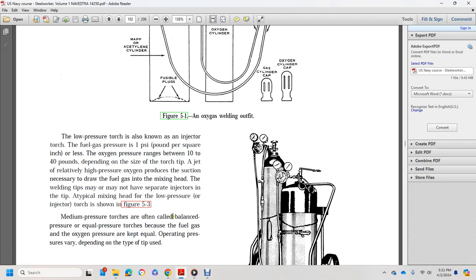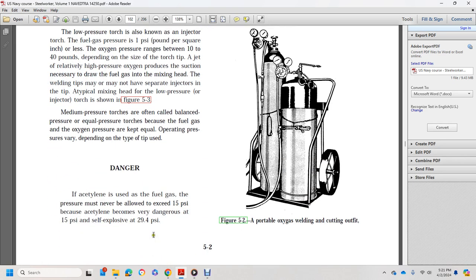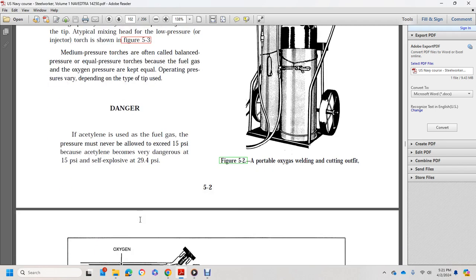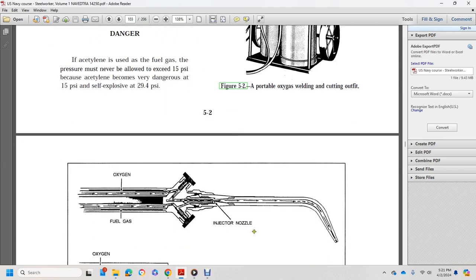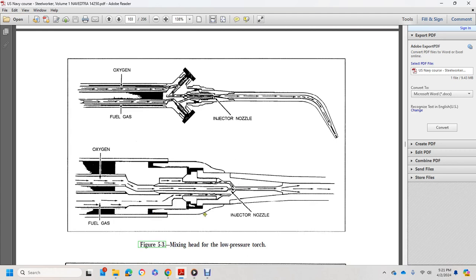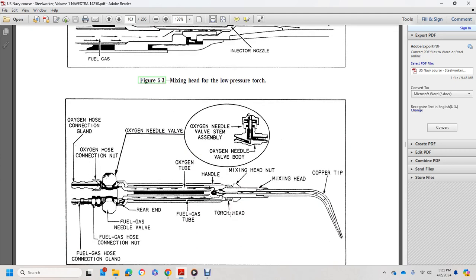Medium pressure torches are often called balanced pressure or equal pressure torches because the fuel gas and oxygen pressures are kept equal. Operating pressures depend on the type of tip used. Danger: the acetylene fuel gas pressure must never be allowed to exceed 15 psi. Acetylene pressure may be very dangerous at 15 psi and self-explosive at 29.4 psi. Oxygen fuel gas injector nozzle.